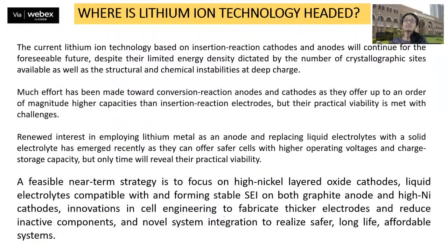So currently, where is lithium-ion technology headed? As I said, the technology based on insertion reaction cathodes and anodes is going to continue in the foreseeable future, despite the limited energy density, which is dictated by the number of crystallographic sites available, as well as the structural and chemical instabilities at deep charge.